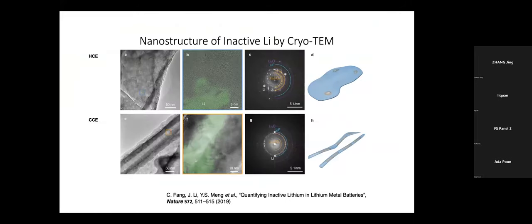Now, our group has really shown that with the cryo-EM, you can then image very, very nicely how the spatial distribution of the SEI component with respect to what we call the dead lithium, so the lithium trapped inside the SEI. So here, the top panel is the lithium that is trapped inside the high concentration electrolyte. The bottom is those whisker type of lithium metal that trapped in the elongated whiskers of these SEI shells.